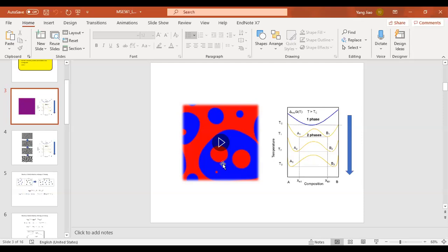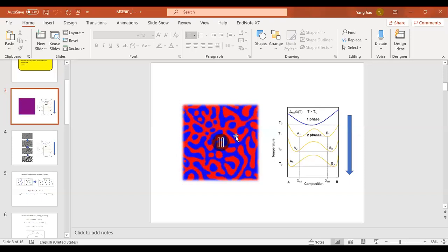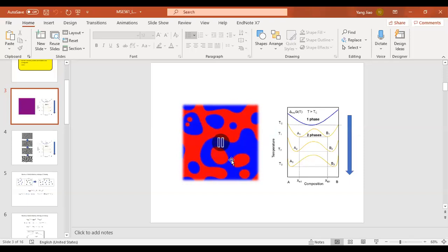Reduced area. Reduce the area per unit volume, right? Initially the interface is not quite important because we have a diffusive interface, but at the end of the separation you have a sharp interface, so we want to minimize that. In this case, there's no way to reduce the energy because the separation has already occurred. So what I can do is reduce the interface area. I can optimize the shape so that it becomes circular, and this will lower the area of the interface, which clearly indicates the role that the interface plays towards the end. Does this make sense, everyone?